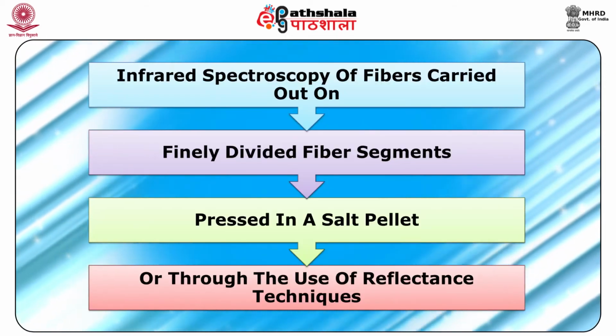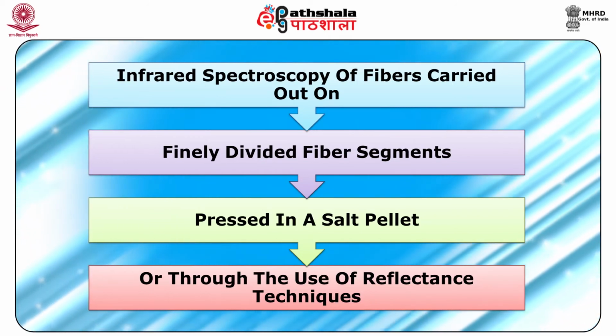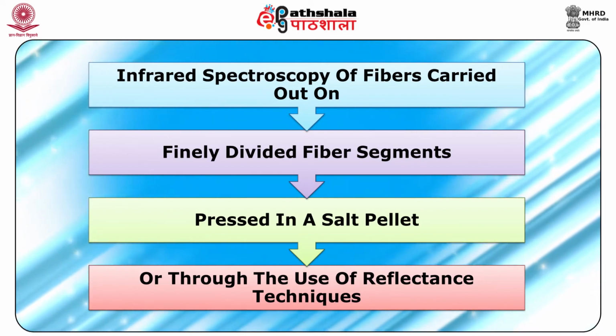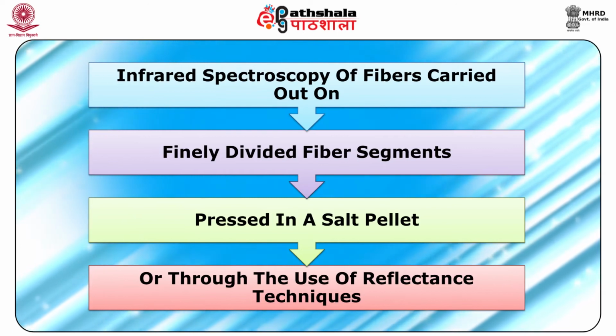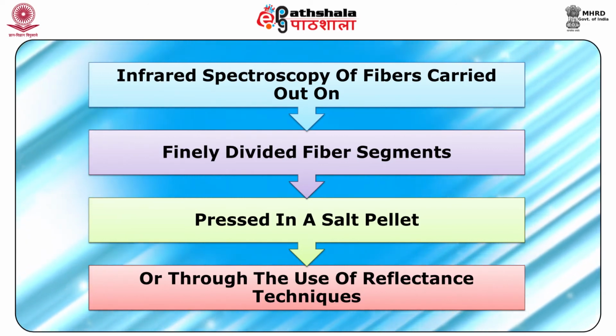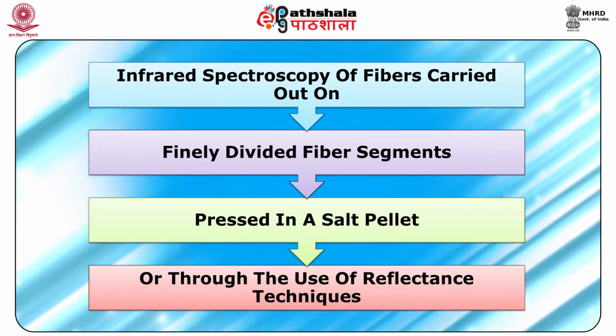Infrared spectroscopy of fibers can be carried out on the finely divided fiber segments pressed in a salt pellet or through the use of reflectance techniques. Functional groups in dyes and finishes can also be detected by this technique.